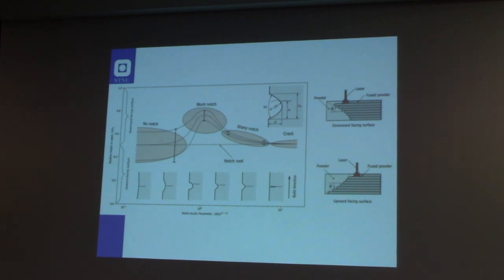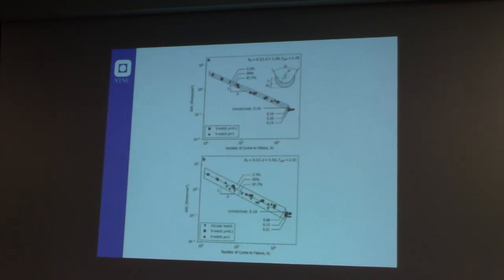And we try to propose a kind of diagram to understand, for no-notch, blunt notch, sharp notch, and crack, what is happening in terms of failure, in terms of mechanism. And after that, we also try to apply the strain energy density. We consider only mode 1 at the moment because the topic is quite new, but actually the results are very promising, and it is very evident that the strain energy density, if used properly, can be a very good tool also for predicting failure under fatigue loading, at least under linear elastic condition for these materials.